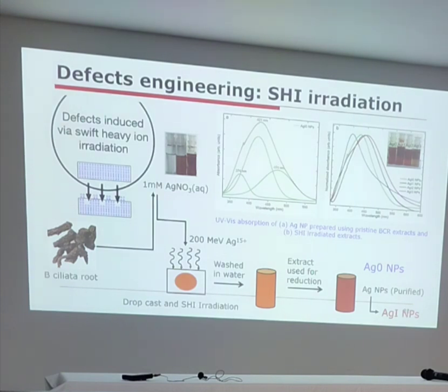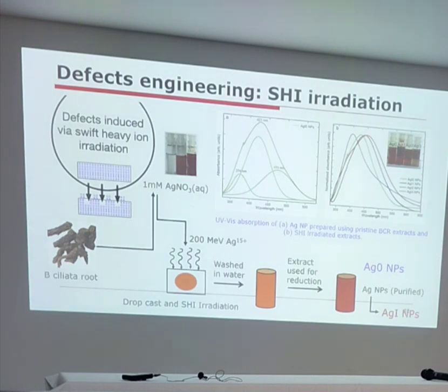That means our theory relatively worked, in which we called one of them AG0, which is the unirradiated nanoparticle, and another one was the AG irradiated nanoparticle. I don't have a picture of this, maybe I'll show that later, but without irradiation we were seeing spherical particles, but with irradiation we started seeing dendrite-like assemblies, where these particles become a nucleus and then start growing just as if they are having wings in the process.